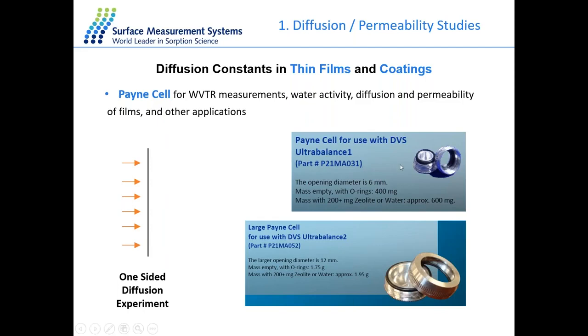And it comes in 2 different sizes. So the small Payne Cell has an opening diameter of about 6 mm and is suitable for both low mass balance and high mass balance. In the case of the large Payne Cell with the diameter of about 12 mm, this cell is only suitable for the high mass balance because it's too heavy in mass.